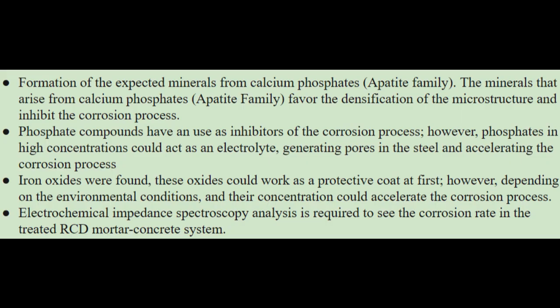Conclusions. By Raman spectroscopy and optical microscopy, formation of the expected minerals from calcium phosphates was found. The minerals that arise from calcium phosphate, in this case the apatite family, favor the densification of the microstructure and inhibit the corrosion process of the reinforcement steel. Phosphate compounds have a use as inhibitors of the corrosion process. However, phosphates in high concentrations could act as an electrolyte, generating pores in the steel and accelerating the corrosion process.